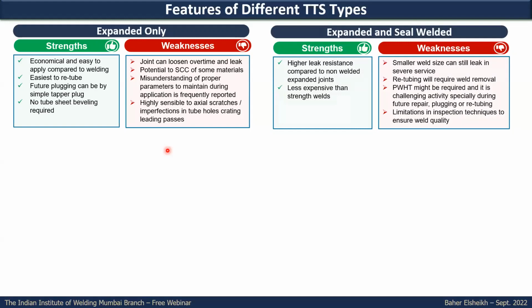Expanded and seal welded is much better compared to expanded only. You will have more leak resistance and sealing. So it is much preferred compared to expansion alone whenever you have a higher critical service, where no tolerance is accepted for a mix between the two sides. The weaknesses of this one: you can consider that the small weld size is still somehow vulnerable to leaking in case there is some issue in the joint. Retubing in the future, you will need to do welding, so some more work is required.